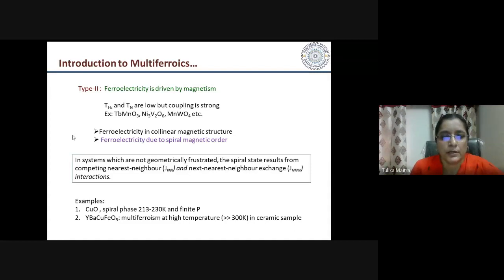The ferroelectricity in these materials is driven by magnetic order. The magnetic order can be of collinear type, or it can be non-collinear or spiral magnetic order. I will discuss the second class of compounds, where ferroelectricity is driven by the spiral magnetic order. The spiral magnetic order can arise in systems which are geometrically frustrated, and I will come to what geometrical frustration is in the second example. But if the system is not geometrically frustrated, then the spiral state can result from competing exchange interactions. If the nearest neighbor and next nearest neighbor exchange interactions compete with each other, then also it can give rise to a spiral magnetic state.